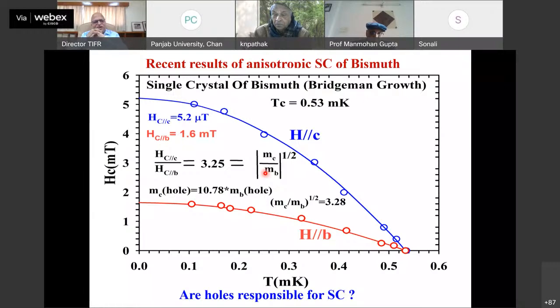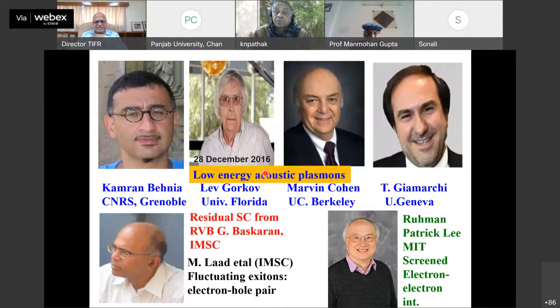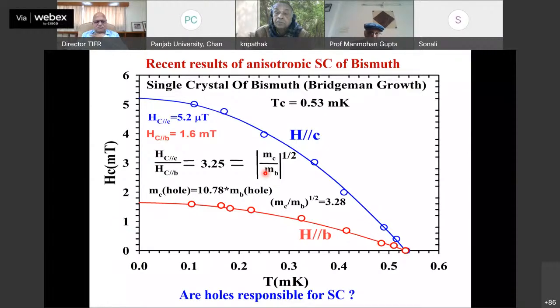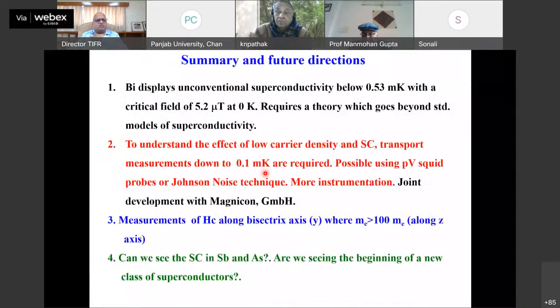Now we have done the anisotropy of bismuth. We can see that the anisotropy is very large, but if you compare the critical fields, we feel that the holes... Bismuth is a compensated metal with equal number of electrons and holes. The effective masses of the hole are slightly heavier than the electrons, and we feel that the holes are responsible for superconductivity, which is what Patrick Lee and his postdoc were saying. As I said, more measurements have to be done, and we hope that this would be taken up by others. So the summary is that bismuth displays unconventional superconductivity and requires a theory which goes beyond the model of superconductors.